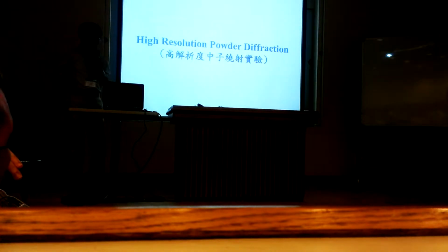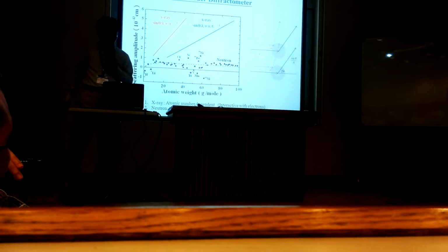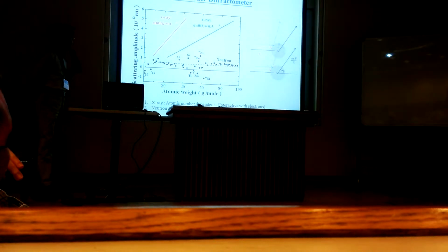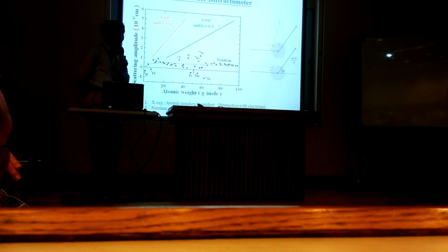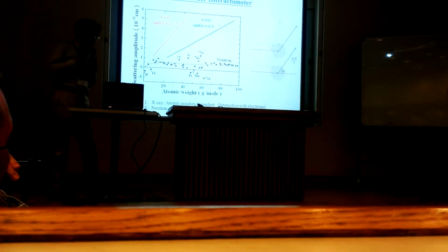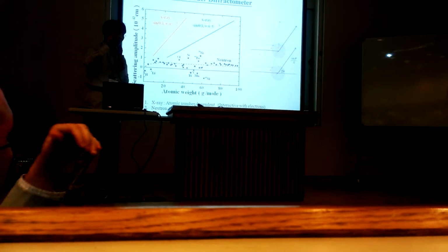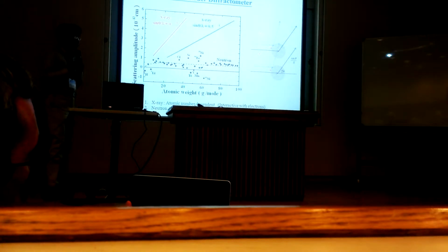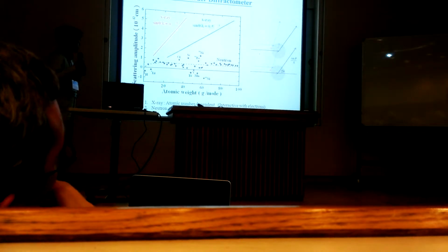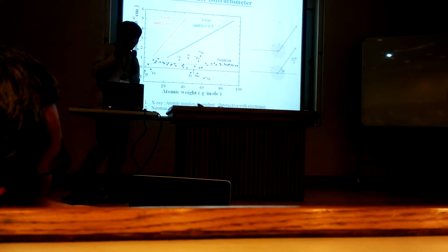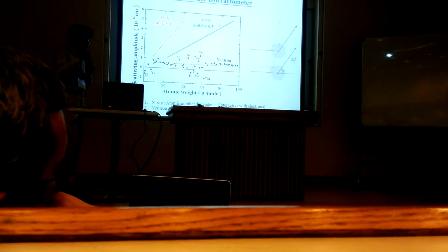So first, I want to talk about high resolution powder diffraction. And this plot already appeared 3 times today, so you will know this is a very important plot. And here I just want to mention a little bit more about when you need to resolve your crystal data, especially for very narrow spacing. Neutron is much better than X-ray, because for X-ray the intensity depends not only on atomic number but also on the angle.